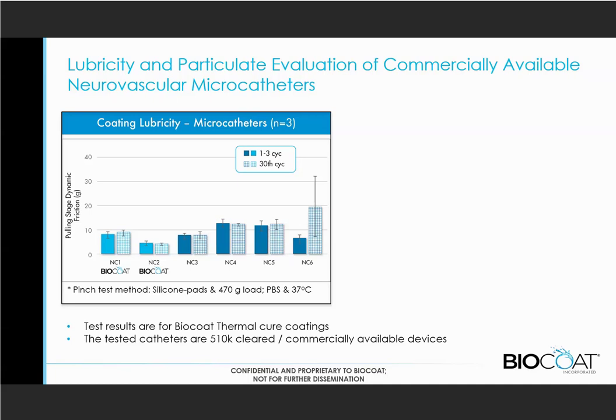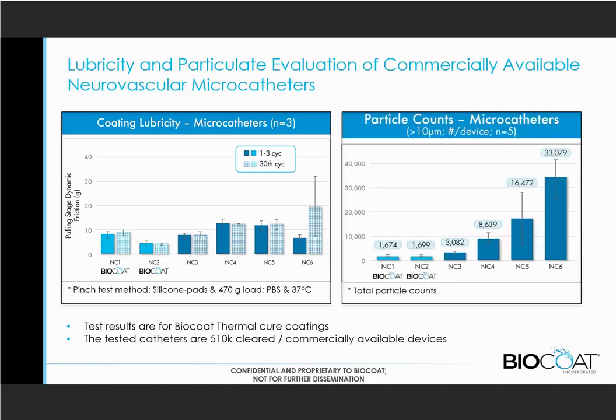So this is how we were evaluating coatings up until the particulate situation came along. But when you add in the particulates, you get a really interesting contrast on these particle counts. Again, these same devices, there is a very large difference in the amount of particles coming off of these devices from the same tortuous pathway, done by the same operator, tested the same way. There's a 20-fold difference in the amount of particles being generated. The NC6, not surprising since the durability is not as good, probably has a lot more particles. But the other 5 also had a 10x difference in the amount of particles being generated, all with essentially the same lubricity and good durability from the friction testing.